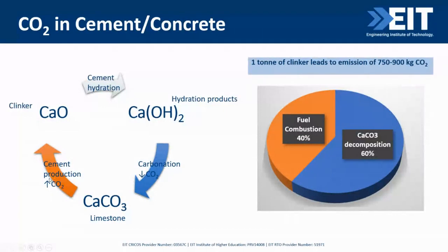This reaction is unavoidable in the manufacturing of cement clinker, and typically one ton of clinker leads to emission of 750 to about 900 kg of carbon dioxide. Among this amount of carbon dioxide, 60% comes from the calcium carbonate decomposition, and 40% comes from the fuel combustion needed for cement production.